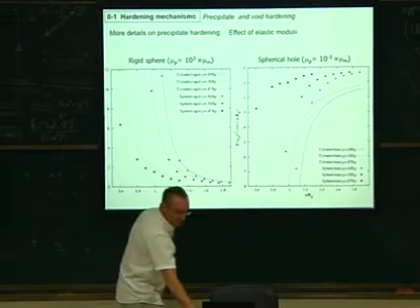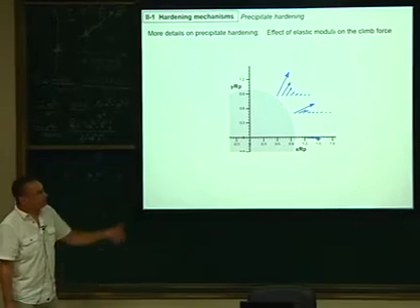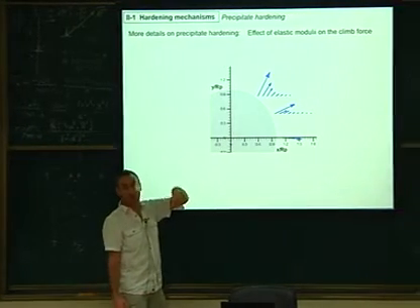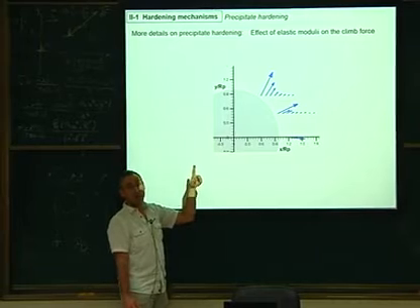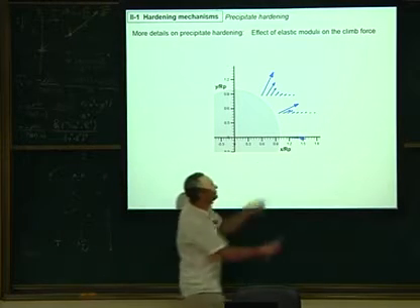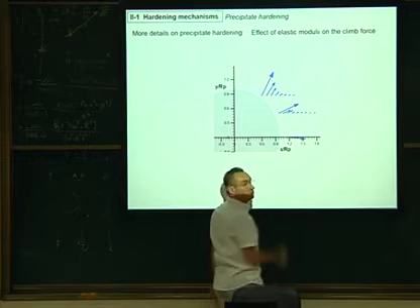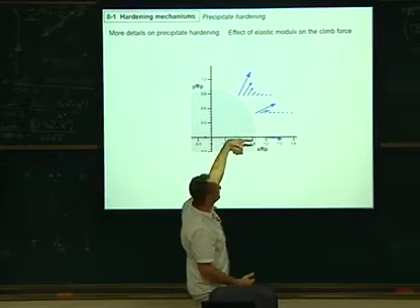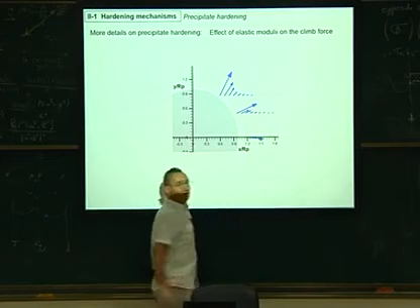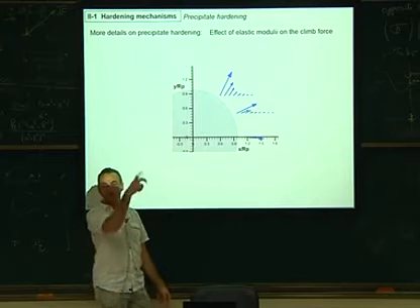So from that, we were able to measure the hardening. What I also wanted to highlight is that this force is not only on the glide, but it can also be applied on the climb component. So this is the Peach-Koehler force, the two components of the force, plotted at different positions of the dislocation. If it's here, there. You see that here it's a pure glide dislocation. It's an edge with the Burgers vector horizontal. And here you can see that in the Peach-Koehler force, there is a component of climb. And if you are even higher, you have a bigger component of climb.